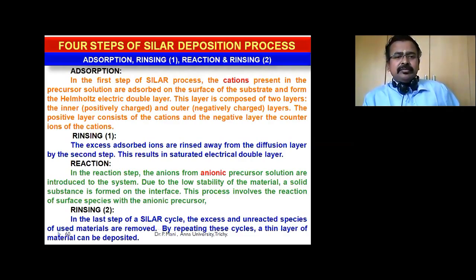And in the reaction step, the anions from the anionic precursor solution are introduced to the system. Due to the low stability of the material, a solid substance is formed on the interface. This process involves the reaction of surface species with the anionic precursor and a second rinsing after the reaction. The excess and unreacted species of the used material are removed in this step. By repeating these cycles, a thin layer of material can be deposited.